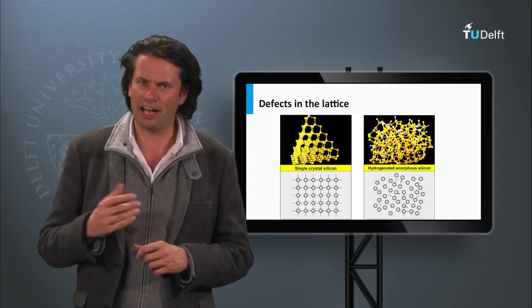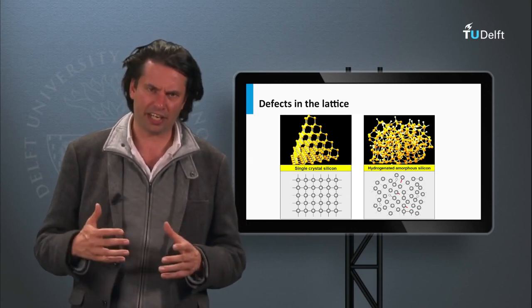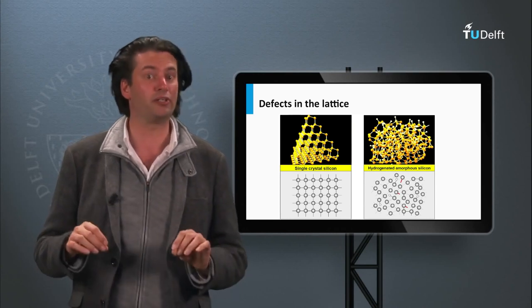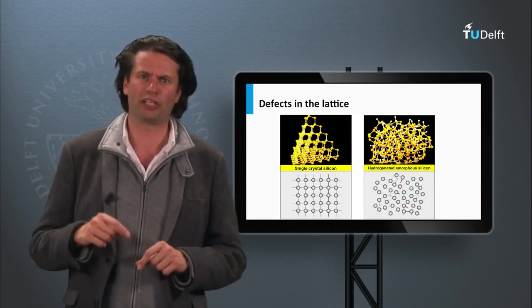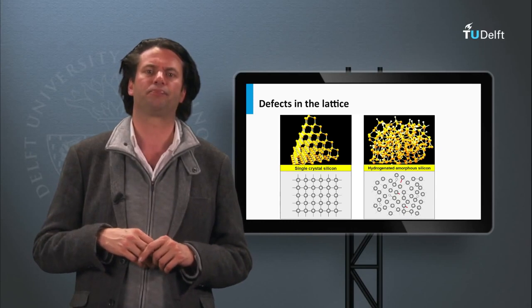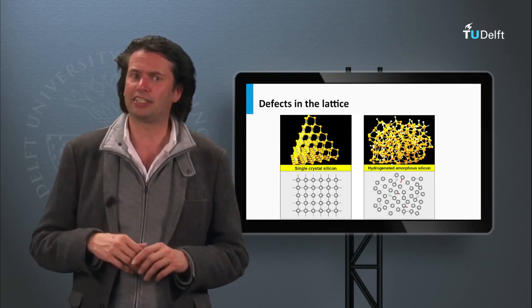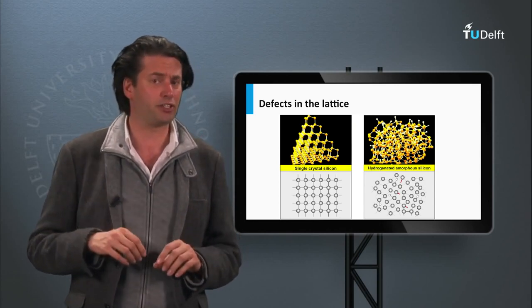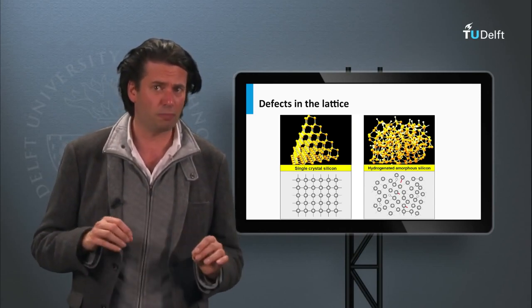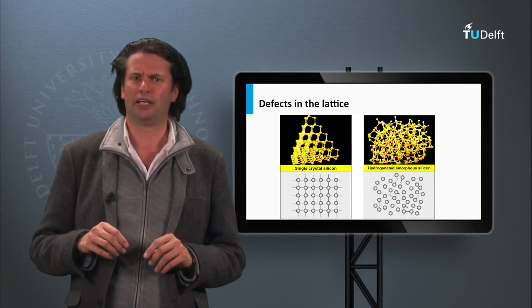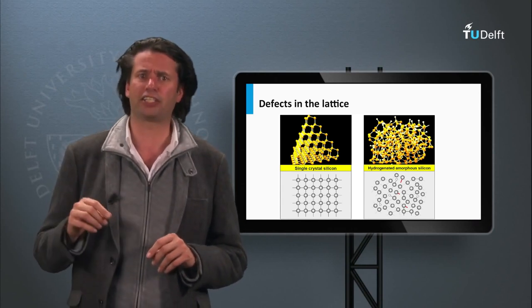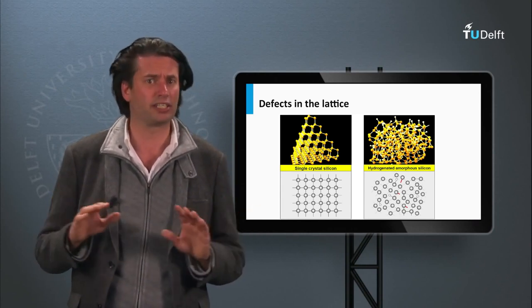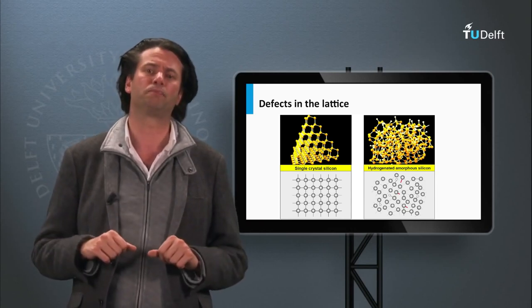This means that the lifetime of the light-excited charge carriers is limited by the Shockley-Read-Hall recombination, which controls the diffusion length. The recombination is so high that the diffusion length of the charge carriers in hydrogenated amorphous silicon is only 100 up to 300 nanometers. This means that the transport of charge carriers in a thick absorber layer cannot rely on diffusion.